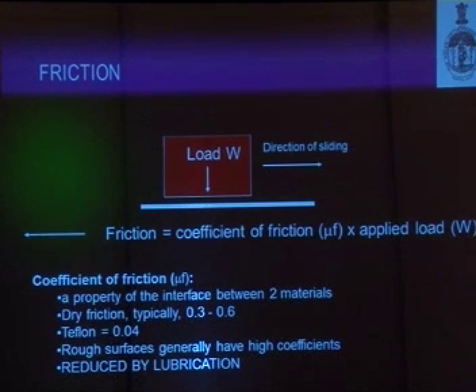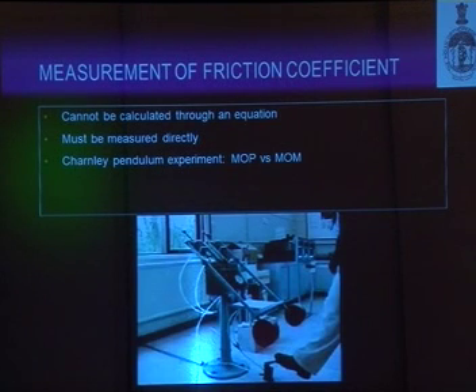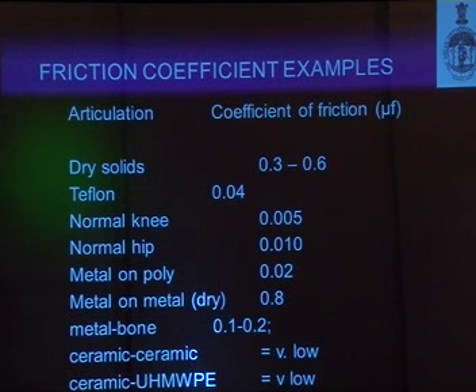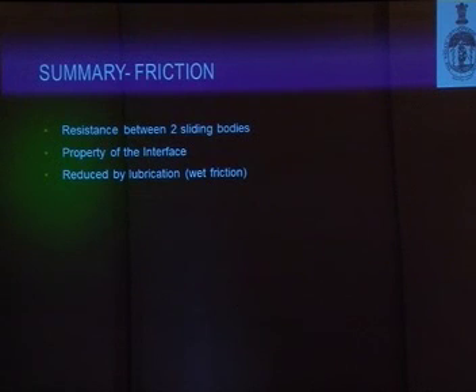Of course, the friction is reduced by lubrication, and that's why we have synovial fluid in our joints. The coefficient of friction can't be calculated through the equation. It has to be measured directly. Now, if I look at the coefficient of friction of a normal knee, it's 0.005, which is very good. And for the hip, it's 0.010. The closest to that, of course, are the articular surfaces. Ceramic is very low. Ceramic on ultra-high molecular weight polyethylene is also very low. In summary, friction resistance between two sliding bodies is a property of the interface and is reduced by lubrication.